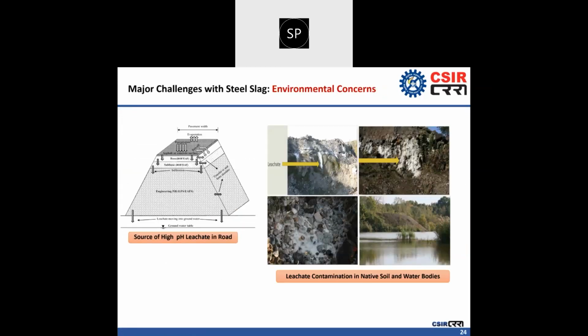Now the fifth one is the presence of heavy metals and the possibility of high pH leaching. In this photograph, you can see that the high pH leachate comes out from the slag deposits in the form of white precipitates. These precipitates can contaminate nearby water bodies and can pose a challenge to the local flora and fauna. Therefore, it is advisable to treat the slag aggregate before its application. Even stable mineralogical phases can be developed by adopting a suitable steel slag cooling methodology, which has been developed as per the type of steel slag by CSIR CRRI and implemented in different steel industries.